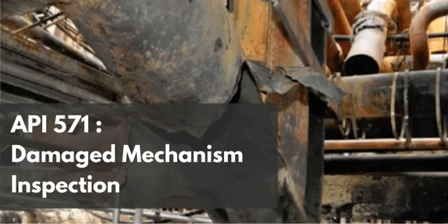Right. A crack might demand an immediate plant shutdown and a cut-and-weld pipe replacement. A localized corrosion groove, while serious, might be evaluated as safe to run for another 6 months with monitoring, or perhaps mitigated by applying an engineered clamp, or, most importantly, by changing the process chemistry to stop the corrosion from progressing. The danger here is staggering.